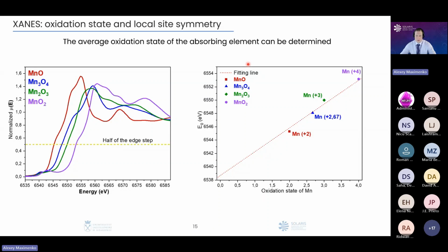I think one of the most important applications of X-ray absorption spectroscopy is defining the average oxidation state of the elements in our compounds. For example, here you could see the position of absorption edges for different oxides of manganese, and you could see that they are separated in energy. When we put them on a graph where on the X axis we have the oxidation state of the manganese atom in this oxide, and on the Y axis the edge position calculated at half of the edge step, we could see a straight line. That's how you could analyze, for example, the average oxidation state of a material which you don't know.